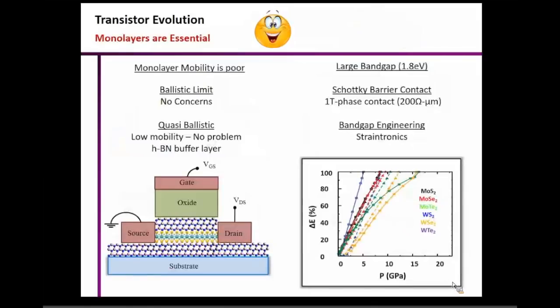But let me also point out that when we talk about monolayers, people will always try to criticize monolayer 2D materials for 2 reasons mainly. One is that monolayers have a poor mobility number, which is true. But I don't think that is actually a concern, because if your devices are working at this 3 nanometer channel length regime, then you are mostly in the ballistic regime. So the mobility really doesn't matter. What matters is your density of states, the number of effective modes, which is proportional to the square root of the effective mass.